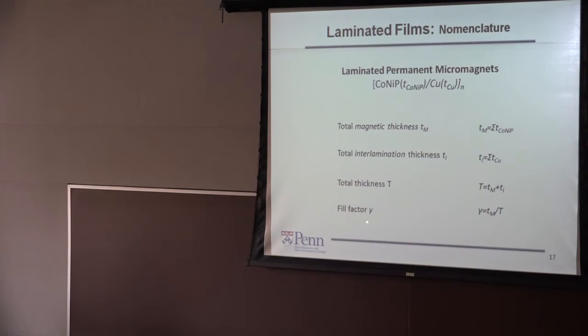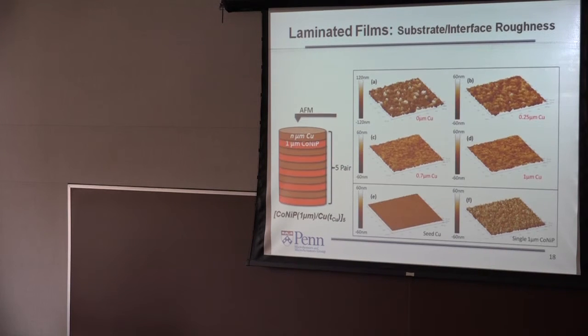And one important thing is the fill factor. It's defined as the total magnetic thickness over the total thickness. So as you see, other than the first layer of cobalt nickel phosphorus, all other magnetic layers are built on the underlying copper layer, right? We know that the interface has an important role in the material properties. So we want to do a controlled experiment to understand the underlying role of this copper interlayer.